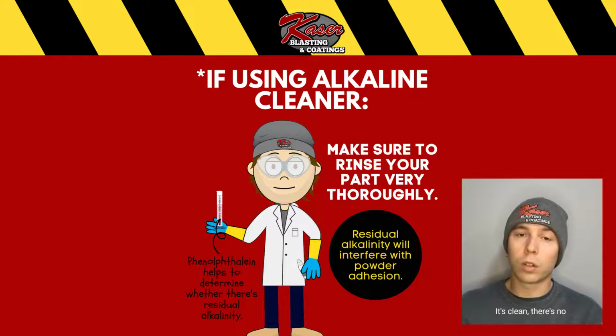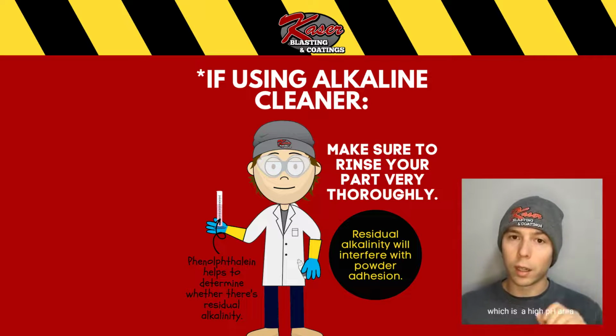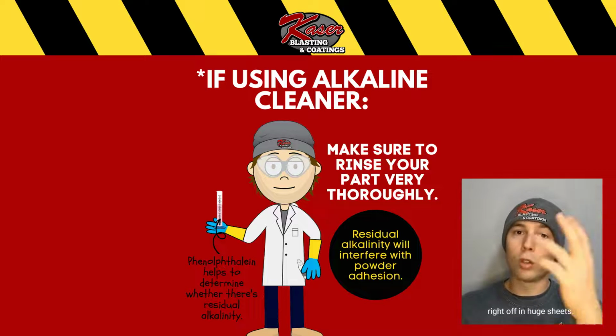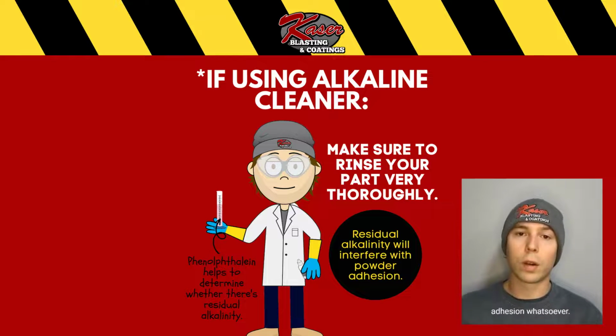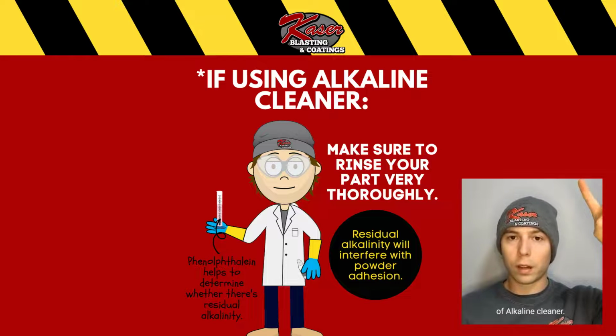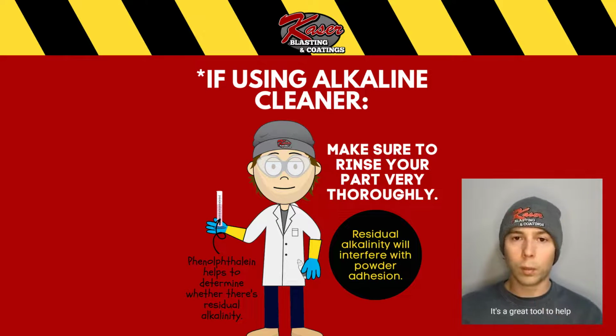It's clean, there's no grease and oils, but that residual alkalinity that gets left behind, if powder coating is applied directly over top of that, the powder coating does not like to adhere to that residual alkalinity, which is a high pH area, essentially. And so the powder will just fall right off in huge sheets, so there's essentially no adhesion whatsoever. So you have to be very, very careful of alkaline cleaner. It's a great tool to help clean greasy and oily parts, but if it gets left behind, you could have even worse problems than you had to begin with when you had grease and oil.